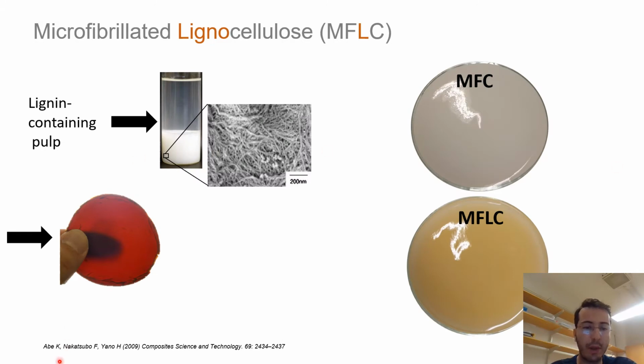For the first time, Kentaro Abe and his co-workers at the University of Kyoto in 2009 tried grinding of CTMP with high amount of lignin, and then they got microfibrillated lignocellulose with quite high residual amount of lignin. They did vacuum filtration on the MFLC suspension and hot pressing to make these films, and they showed that these films are quite strong and promising. You can see in this picture that when we have lignin present, because of the characteristic of lignin, it is rather brownish.